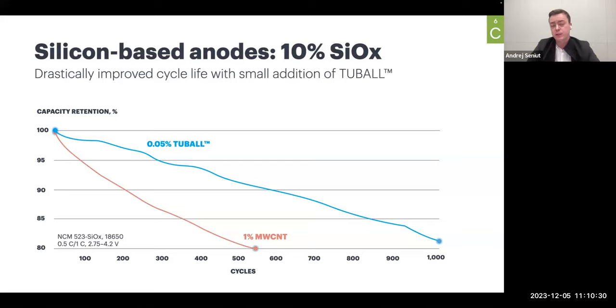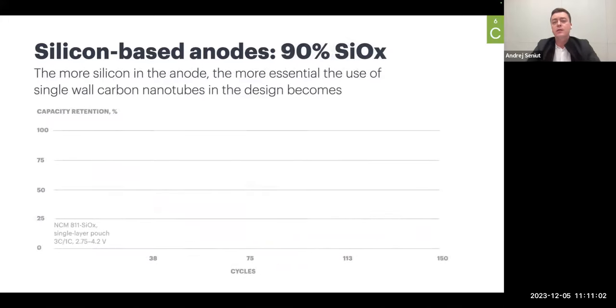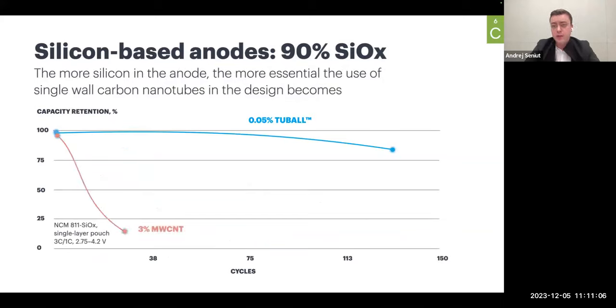In this case, only 0.05% of TUBALL, which is a trademark of our product, allowed to improve the cycle life almost twice and reach a cycle life equal to 1,000 cycles, whereas multi-wall carbon nanotubes at 1%, so a 20 times higher dosage, allowed to reach a cycle life of only 550 cycles. But what's very important and essential to understand the areas of application of single carbon nanotubes is that the more silicon is in the battery, the more pronounced is the effect. In this case, this is a 90% silicon oxide battery. And in this kind of system, multi-wall carbon nanotubes do not work at all. The same goes for few-wall carbon nanotubes, and for some less flexible, less long structures. Whereas single carbon nanotubes continue to work.